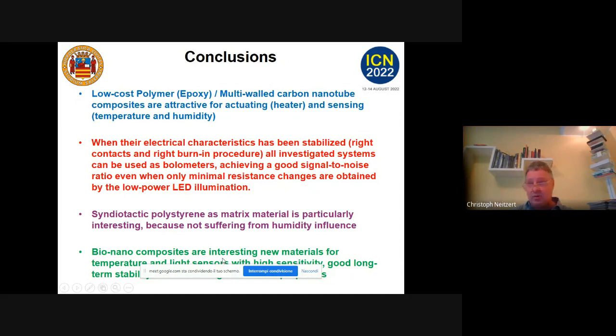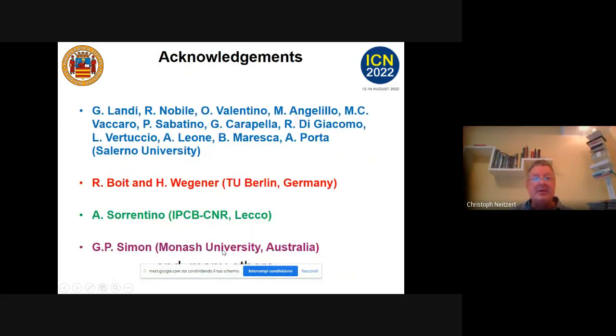For the carbon nanotube, I have to say we have to stay very close to room temperature. We cannot go to 50 degrees already. It starts, 40 degrees is okay. It's like a living organism. You shouldn't go over 42 degrees. Then we end up not only in the hospital. Therefore, what is happening then? The humidity is important for the sensing, and it's also extremely dependent on humidity. This we found out. I didn't show it here. Thank you very much.